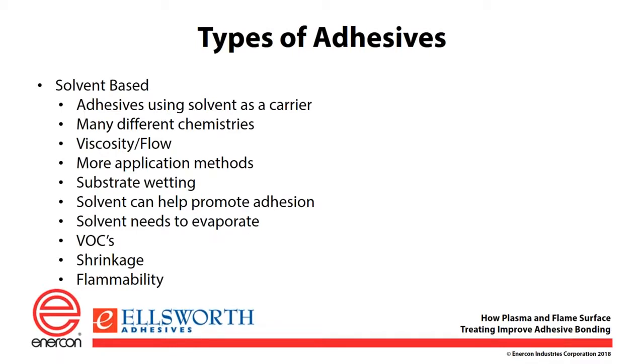Because you have solvents present, you have volatile organic compounds, so you have to deal with possibly regulatory issues related to that. Shrinkage is common because you have solvent that has to leave the system, so it's going to cause shrinkage of the material. And because solvents are present, you have flammability issues.